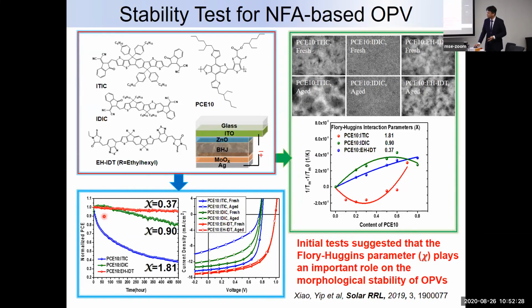And then if the material tends to phase segregate, then when you have light, we provide energy to that, and they start to degrade. The morphology degrades significantly, so they lose the interface, and then the performance continues to drop. So the interface between donor and acceptor material is one important factor governing the morphological stability of the device.